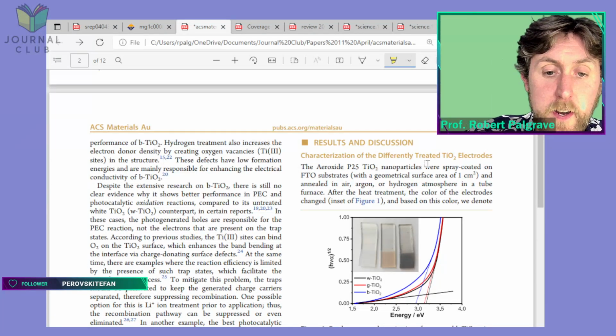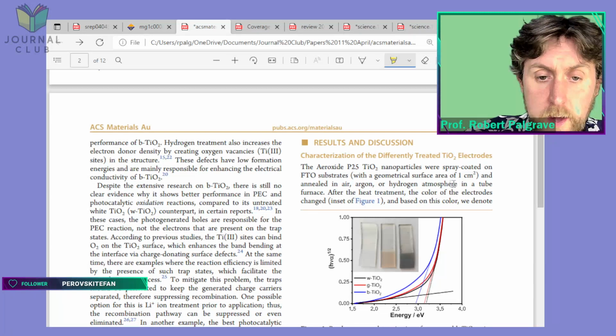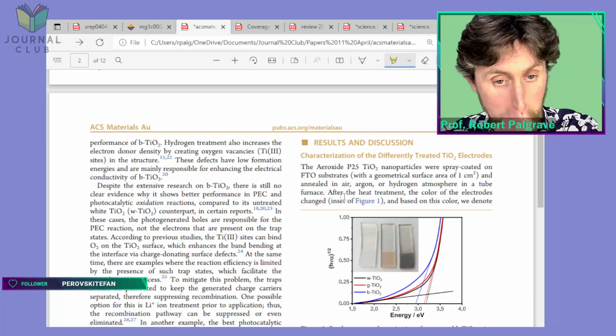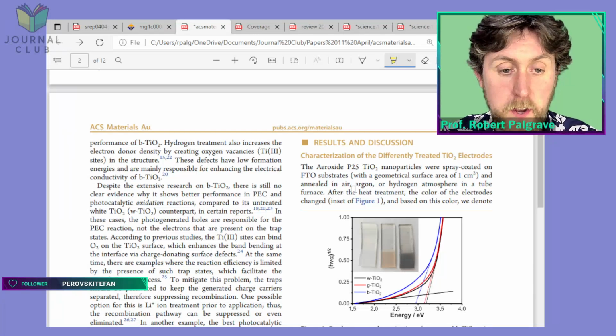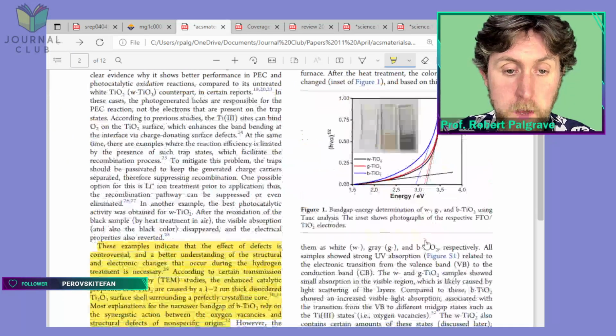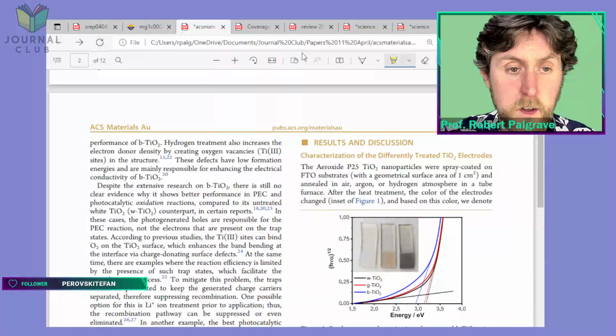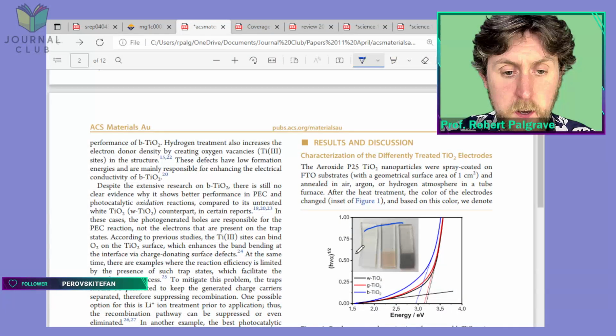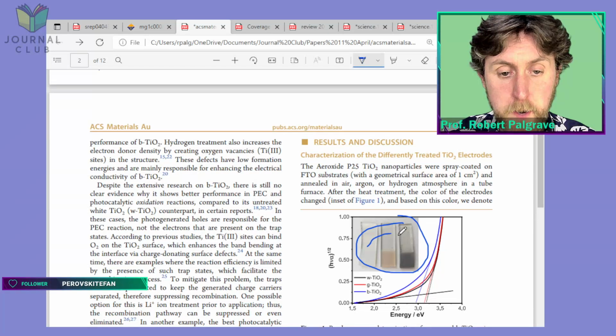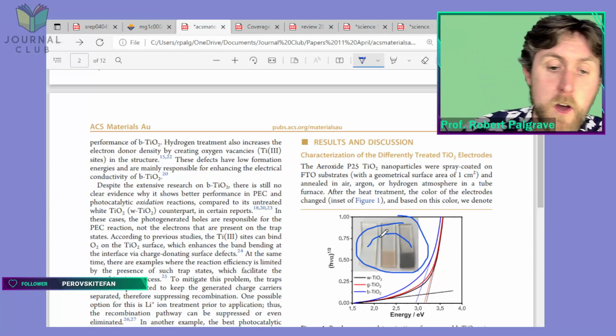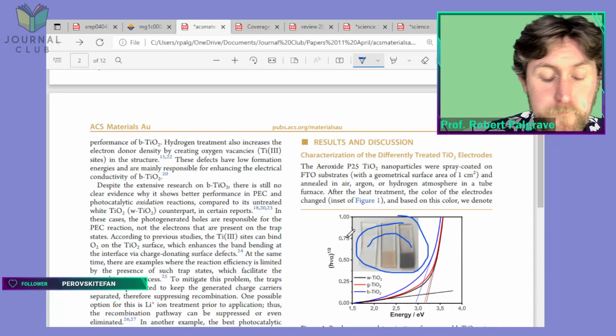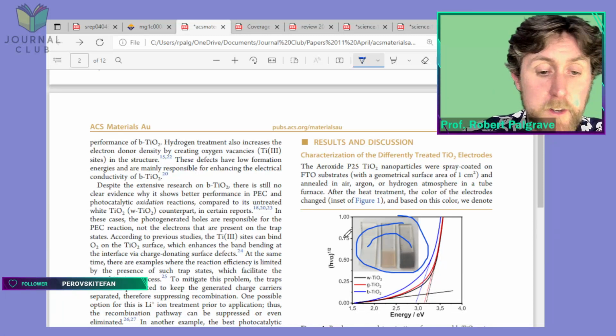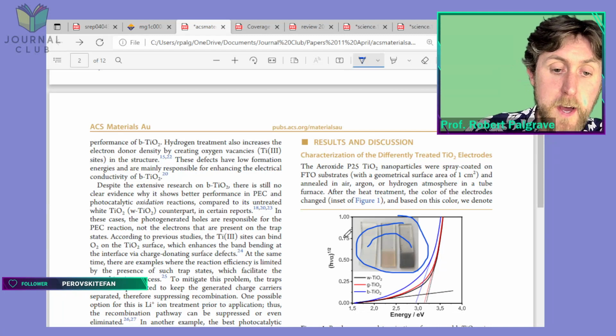So the P25 nanoparticles are spray coated on FTO and annealed in air, argon or hydrogen atmosphere in a tube furnace. They just told us that already. After the heat treatment, the colour of the electrodes changed, in figure 1. So just in terms of the colour, we have pretty much a similar change, at least from white to black, that we saw in the 2011 paper. So annealing, heating up under hydrogen, causes this colour change from white to black.